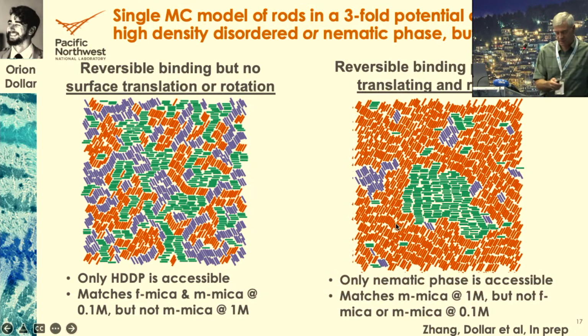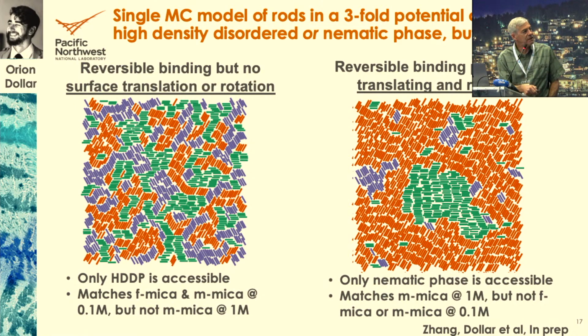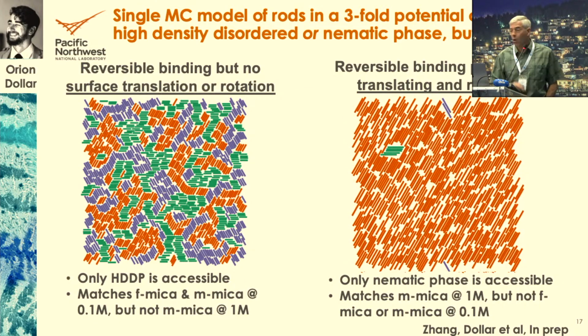What happens is, unfortunately I can't show you. In this case, it starts out like this, but the red domain takes over, and you end up with all co-aligned, because that's the lowest energy state. Entropy determines that. But you can't have both cases, right? It's either one or the other. Either they have mobility or they don't.